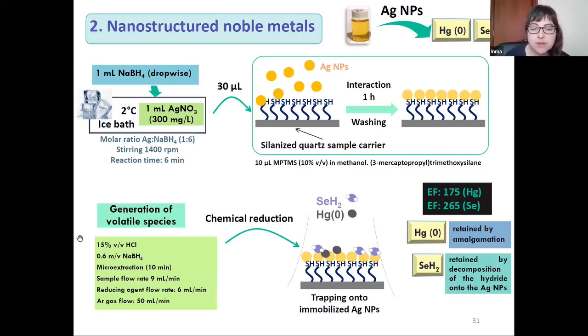Then, using the scheme explained in the previous slide, we can see how the generation of volatile species is performed. In this case, we use 15% of hydrochloric acid in the sample solution, and 0.6% mass/volume sodium borohydride as reducing agent. And here we can see also the different flow rates of the sample, the reducing agent, and also the argon, which is the carrier gas. Then after generation of the volatile species, these vapors are retained onto these silver nanoparticles as hydride of selenium and also mercury vapor. And they were retained by two different mechanisms. In the case of mercury, it is by amalgamation, and in the case of selenium hydride, it is by catalytic decomposition of this hydride onto the silver nanoparticles.